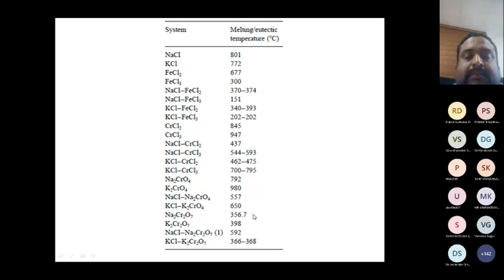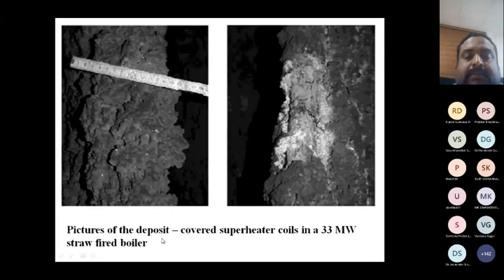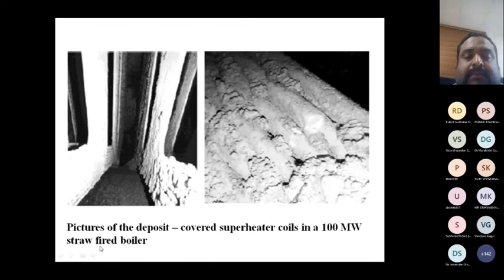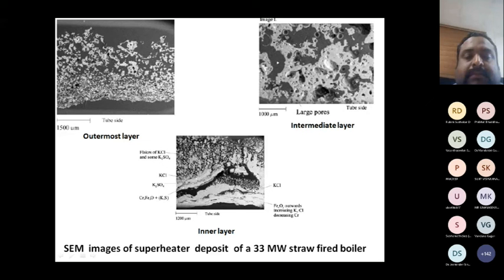The reason being, the potassium chloride melting temperature is 772. But if you see the potassium chloride eutectic, 202. The eutectic mixture of potassium chloride and iron chloride, ferric chloride, has a very low melting temperature. Individually, the potassium chloride melting temperature is 772, but in the form of a mixture, a eutectic, it has a very low melting temperature. So these pictures show the deposit covered superheater coil of a 33 megawatt straw-fired boiler, then a 33 megawatt straw-fired boiler, and a 100 megawatt straw-fired boiler with superheater deposit. This is an SEM picture of the 33 megawatt straw-fired boiler.